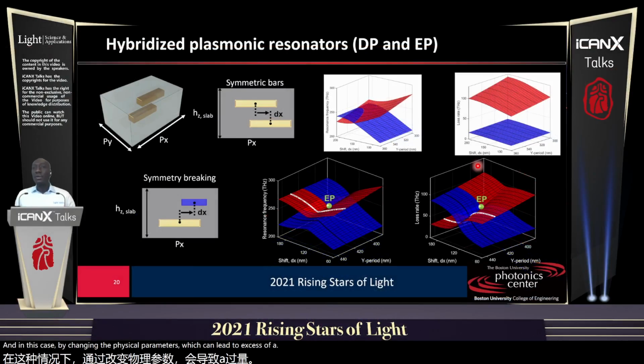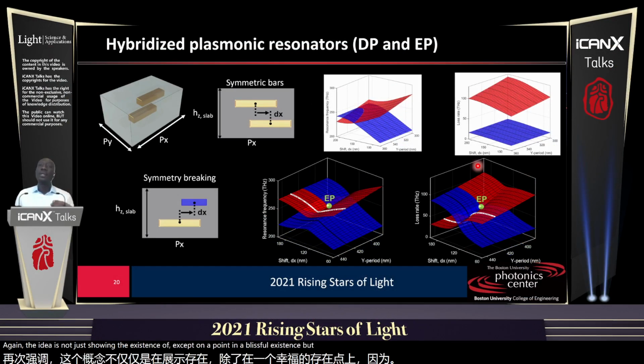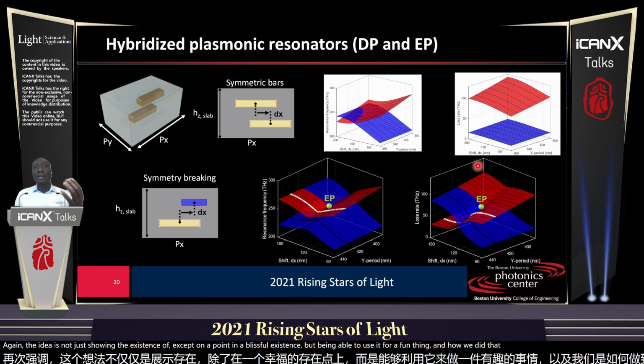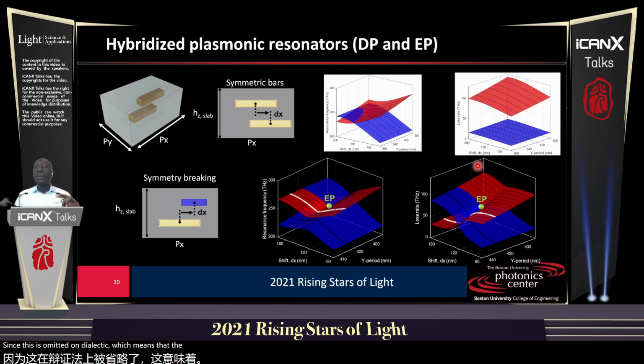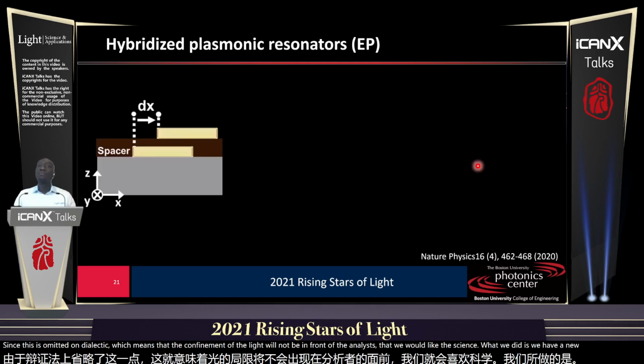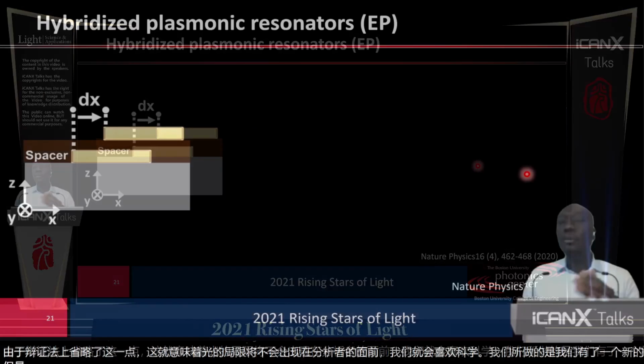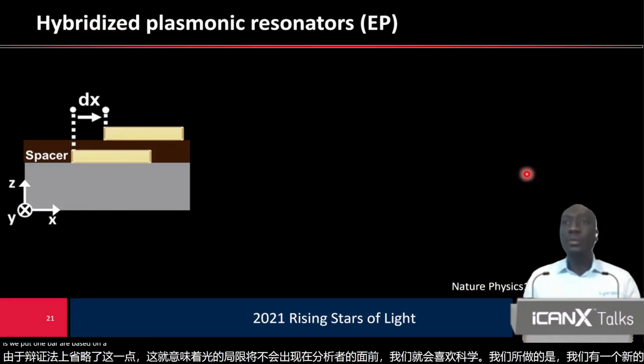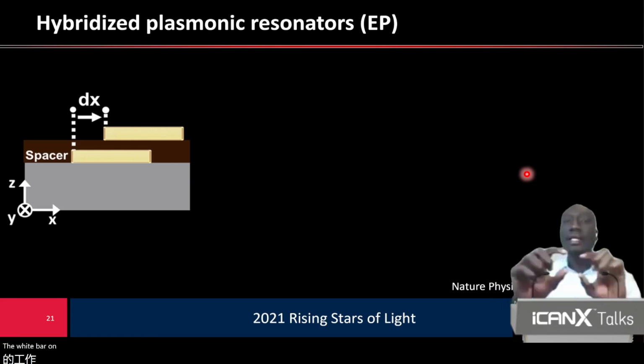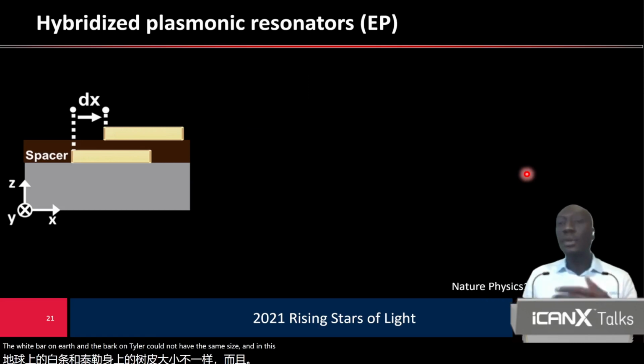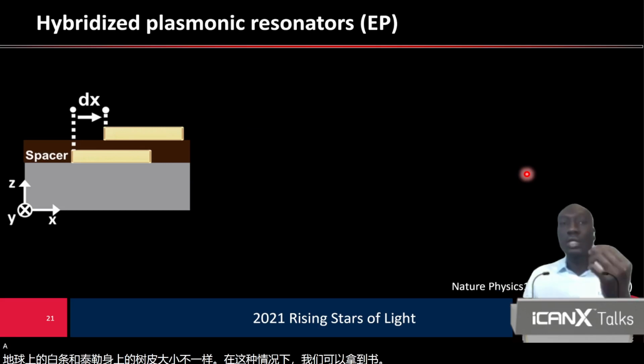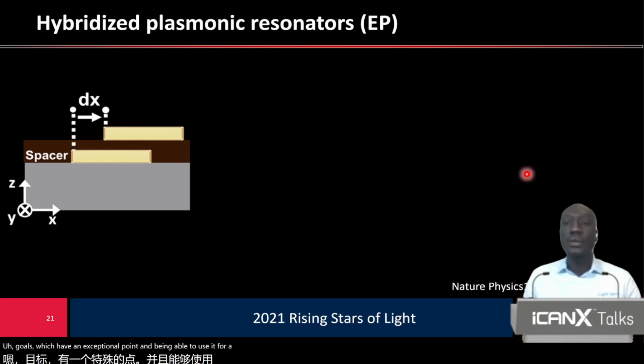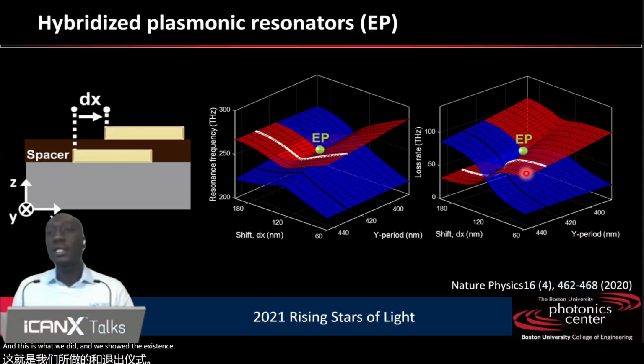We have crossing and avoided crossing on one side, and in the imaginary part, the opposite. Again, the idea is not just showing the existence of an exceptional point in a plasmonic system, but being able to use it for sensing. And how did we do that? Since this is embedded in a dielectric, which means that the confinement of the light will not be in contact with the analytes that we would like to sense, we have a new configuration with two bars of the same size, but we break the symmetry by putting one bar embedded in a dielectric, which is as if the bar on air and the bar on dielectric don't have the same size. In this case, we can reach the two goals, which is having an exceptional point and being able to use it for a sensor. And this is what we did, and we show the existence of the exceptional point.